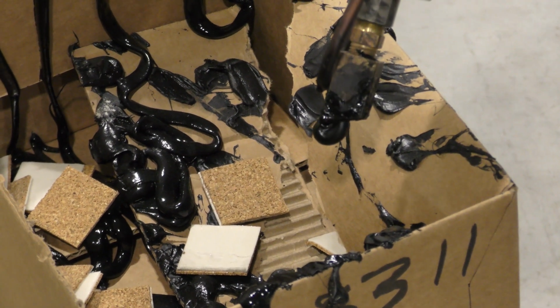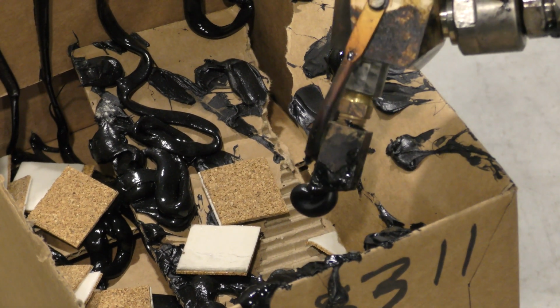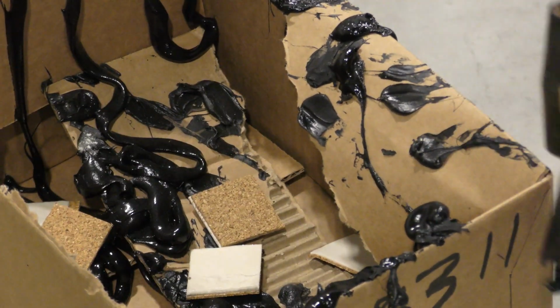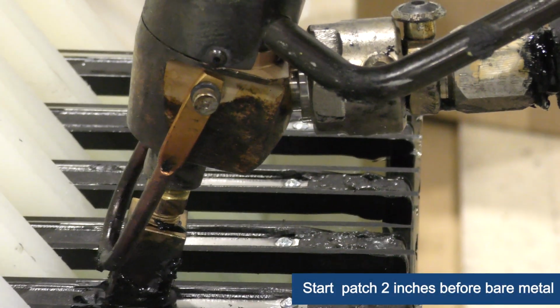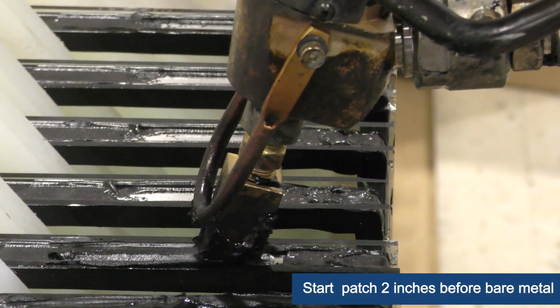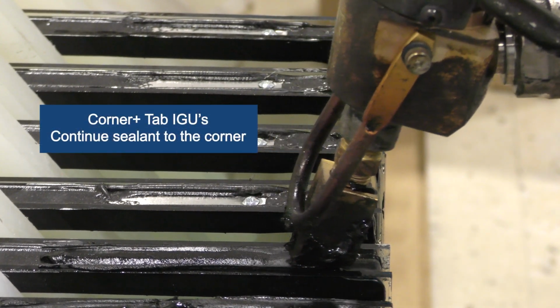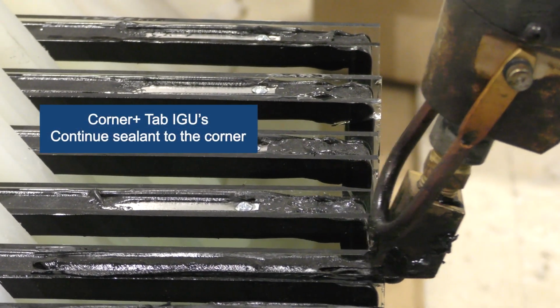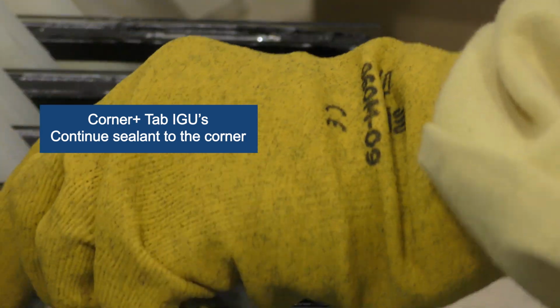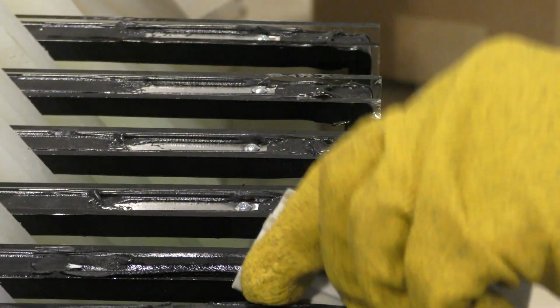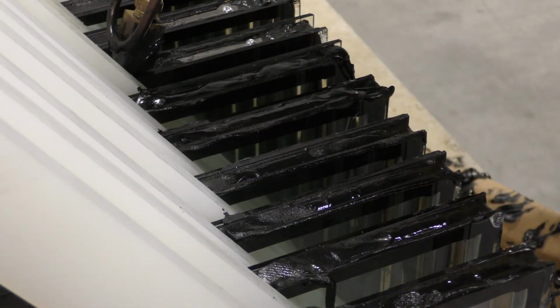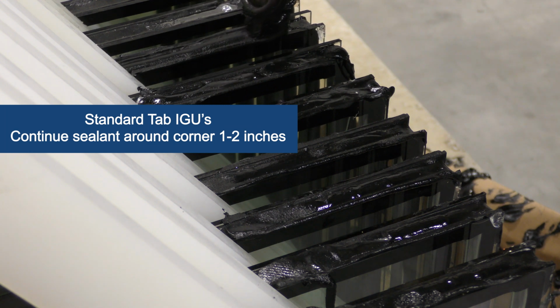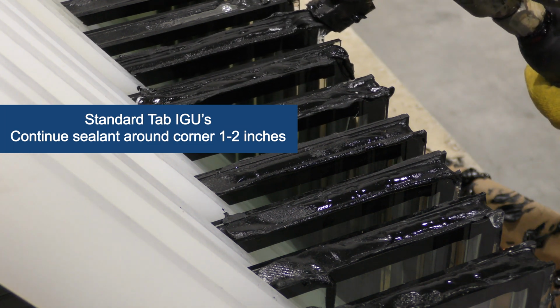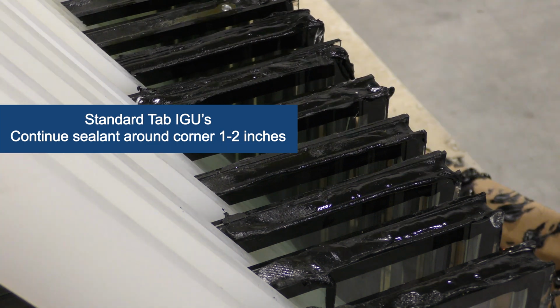Begin by purging some material at the tip to ensure the material is flowing freely with no lumps and the material at the tip is hot. This should be done anytime the handgun sits idle for more than a few minutes. Immediately begin applying hot sealant to the IG unit by placing the nozzle tip on the unit about 2 inches before any bare metal, pulling the trigger, and slowly moving the gun towards the corner. If the tab is a standard tab, continue the patch around the corner slightly, 1 to 2 inches.